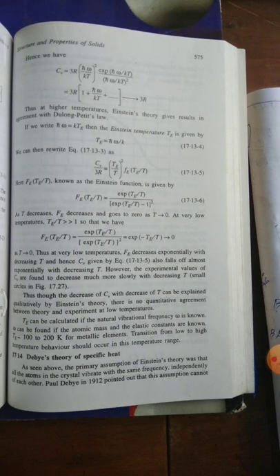Next, Cv by 3R is equal to (θE/T) squared FE(θE/T). Here FE(θE/T), known as the Einstein function, is given by FE(θE/T) equal to exp(θE/T) by exp(θE/T) minus 1 whole squared. As T decreases, FE decreases and goes to 0 as T tends to 0. At very low temperature, θE/T gets much greater than 1, so that FE(θE/T) is approximately exp(θE/T) by exp(θE/T) squared.